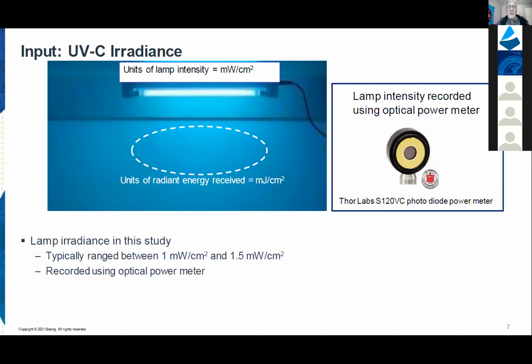And the units are milliwatts per square centimeter. Another way of looking at a milliwatt per square centimeter, though, is a millijoule per second per square centimeter. And that's how we get to the amount of light delivered. So assume, just as an example, that the irradiance of the lamp is 1 milliwatt per square centimeter, and we hold it over this area. Assume that dashed line is just a square centimeter. Use your imagination. But basically, if we hold it over that for 10 seconds, we now have 10 millijoules of radiant energy absorbed by that surface.